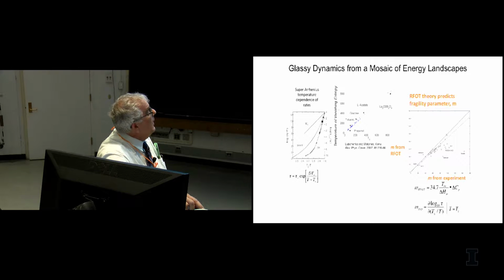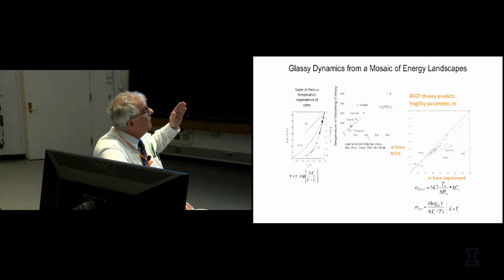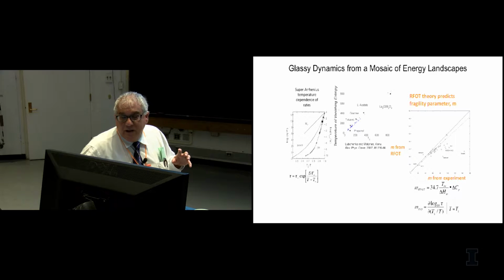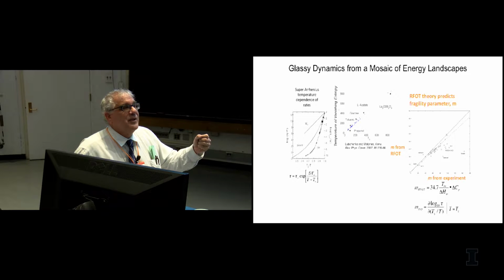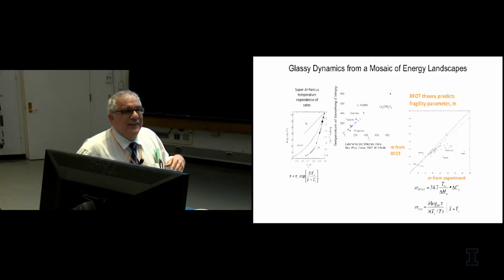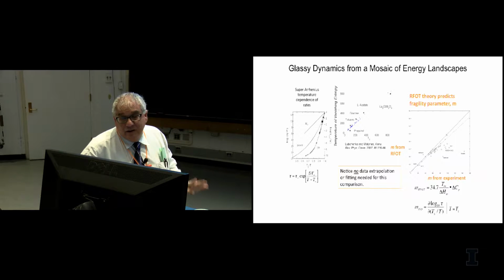The reason why there's this dependence entirely on the entropy is that the free energy cost of making an interface is primarily also entropic. And it depends on this cost to localize a particle to a Lindemann length. A Lindemann length is about 1/10 of a particle spacing. It depends logarithmically on it. And so even if you're off by factors of 2 in the Lindemann length, you're only off by a little bit in the surface energy. And again, this comparison involves no extrapolation at all.